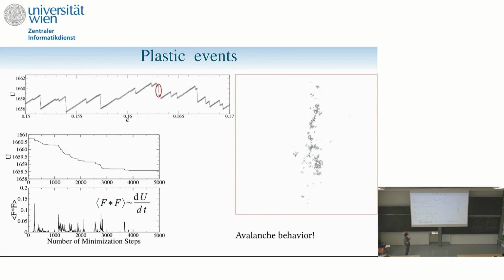So every step I minimize energy, right? I take this drop and I look at what happens to energy during minimization with conjugate gradients. What you see is that you have something very intermittent. Here the system is escaping very slowly the unstable point, and then finds, boom, something interesting, and then da-da-da-da-da, and then at some point believes that maybe, can I stop there? Should I stop? No, it's still not flat enough. And so on and so forth. You have this burst of energy dissipation, which shows that you have this intermittent dynamics of energy descent.